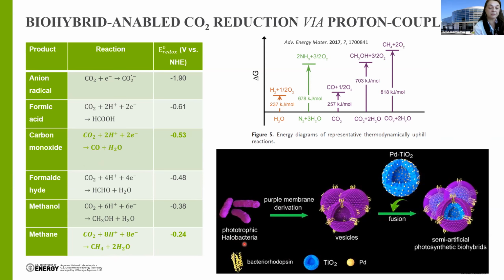Inspired by the light driven proton pumping activity of our purple membranes, we came to this scheme. We isolated membranes from halobacteria and reconstituted them into lipid vesicles. In this case we did not work with just P25 titanium dioxide, but came to need a hollow mesoporous structure, and instead of platinum co-catalyst we utilize palladium since it's more selective for CO2 reduction rather than hydrogen generation. And the last step is fusion of both soft and hard material into a biohybrid.